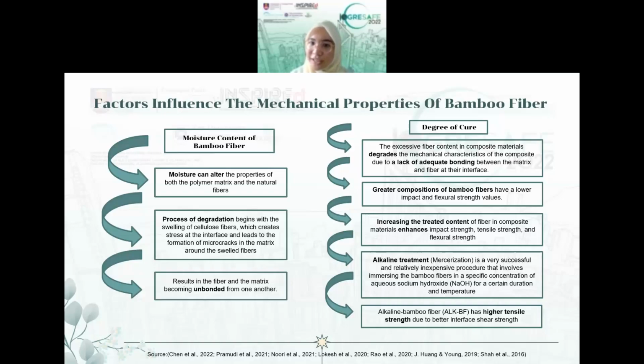So for the degree of cure, excessive fiber content in the composite material degrades the mechanical characteristics of the composite due to lack of adequate bonding between the matrix and the fiber interface. A greater composition of fiber will have a low impact and flexural strength value. But increasing the treated content of the fiber in the composite material will enhance the impact, tensile strength, and flexural strength. Also, alkaline treatment is a very successful and inexpensive procedure, involving immersing the bamboo fiber in a specific concentration, such as sodium hydroxide, for a certain duration and temperature. It is also proven that treating the bamboo fiber with alkaline will improve the tensile strength due to better interface shear strength.